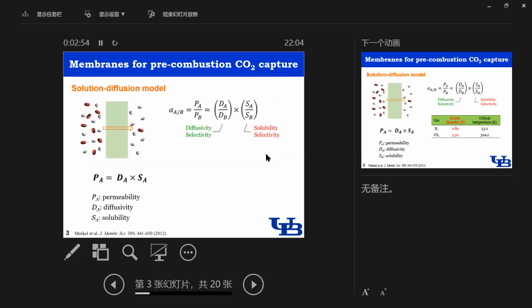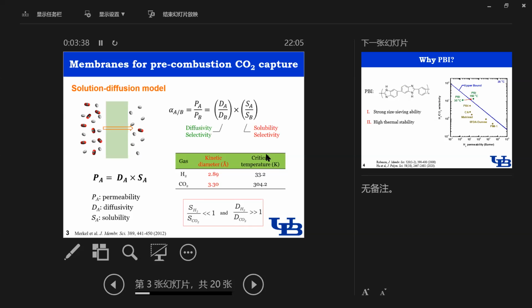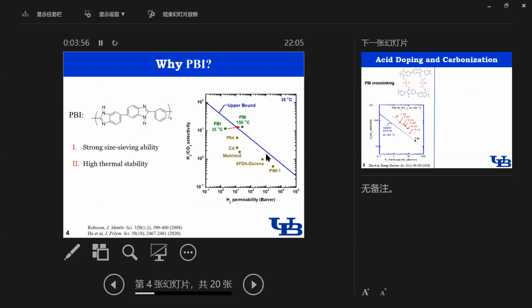As we know, there are three main ways to capture CO2 from coal-fired power plants. One is pre-combustion CO2 capture, where fossil fuels are gasified to produce hydrogen and CO2. And as we all know, gas transports through membranes based on the solution-diffusion model. Gas permeability depends on gas diffusivity and gas solubility, and gas selectivity depends on diffusivity selectivity and solubility selectivity. As hydrogen has a smaller molecular size while CO2 has better condensability, hydrogen CO2 solubility selectivity is always below 1, while hydrogen CO2 diffusivity selectivity is above 1. So if we want high hydrogen CO2 selectivity, we should enhance the size-sieving ability to achieve high diffusivity selectivity.